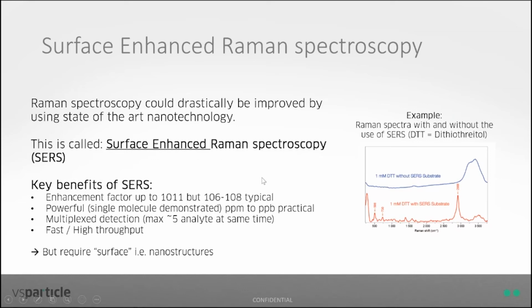So what are the key benefits of SERS? The first one, of course, is the enhancement factor. It's 10 to the power 11, but on average you see a 10 to the power 6 to 10 to the power 8 enhancement of your Raman signal. It's very powerful, so it has been proven to even do single molecule detection, going down to parts per million or parts per billion is practical. So you can do multiplexing, so you can measure different analytes at the same time, especially if the peaks of the analytes are not in the same area, otherwise they are overlapping. And again, it's really fast, so it gives you the possibility to do high throughput experimentation or high throughput analysis.